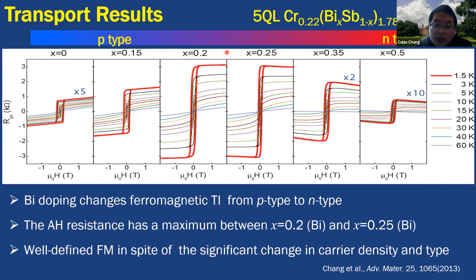You know that we want to achieve this kind of quantum anomalous Hall effect, we need to perform the transport measurement. So we grow the material on some insulating substrate. So here, let's take a look at the transport phenomena. We can see that this is the 5 quintuple layer chromium-doped bismuth antimony telluride. We systematically change the bismuth antimony ratio.